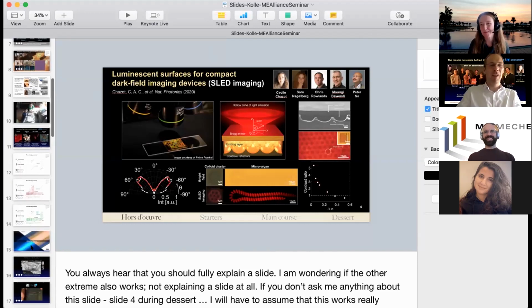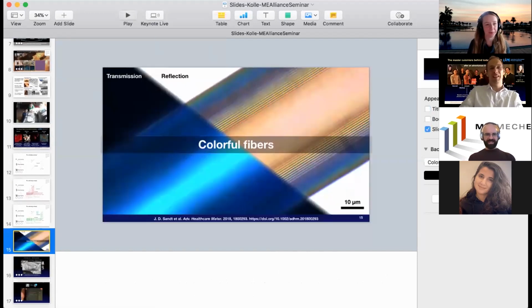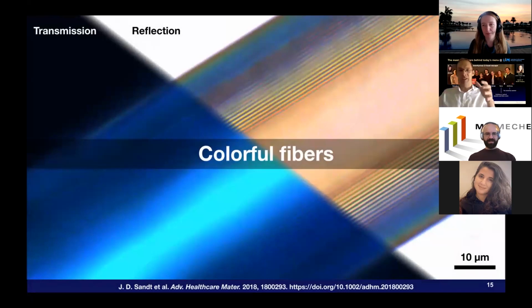Great question. It's all mechanical. Think of this as a spring. It's almost like the deformation in the fibers. You can write down stress is equal to an elastic modulus times the deformation, right? So there's no phase lag in that, unless you go to really high frequencies. So when you push on this material, you get the color right away for the deformation that you create on that time scale. So I think we haven't pushed any limit in terms of finding out at which point we create sort of a lag in response.